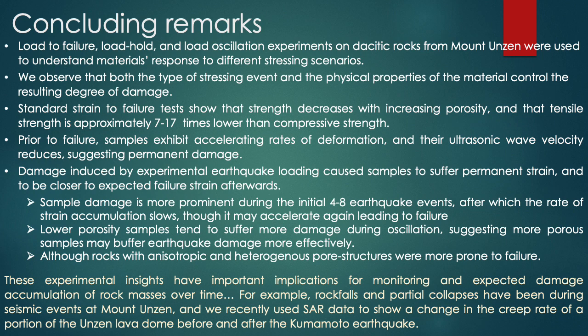The most susceptible materials to failure were anisotropic banded fabrics, which comprise heterogeneous dense and porous layers, and although the scaling of such an observation is yet to be fully addressed, this suggests that heterogeneous masses, such as the Mount Unzen lava dome, may be particularly susceptible and unstable under loading events. Load oscillations cause strain rate to increase in the samples, and in the case of samples that failed, this increasing strain rate accelerated prior to failure.